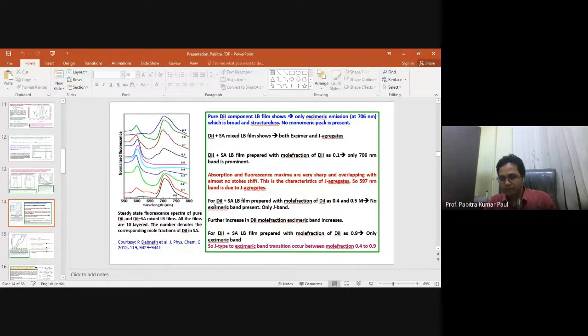From the aggregated species, for the mole fractions 0.4 and 0.5, no excimer emission band is present. So this is very interesting. Only the J band is present, you see, the color is magenta or maybe sky blue. In these two curves there is only the J band, and no excimer band, that is, the 706 nanometer band is not present. So it is mole fraction dependent.